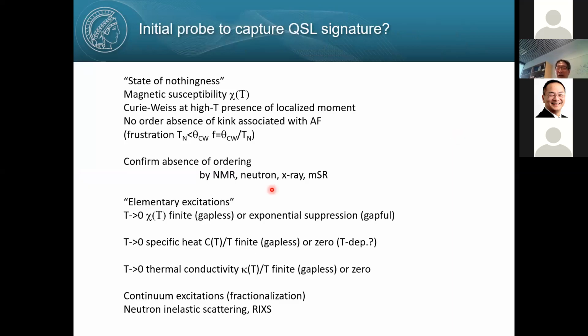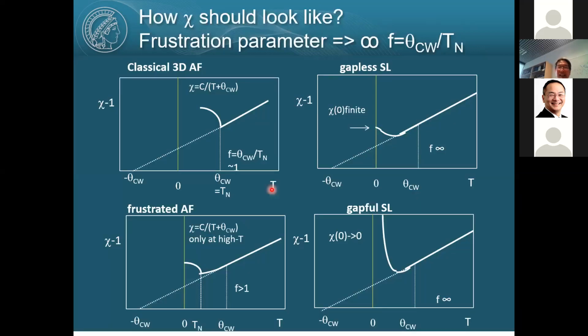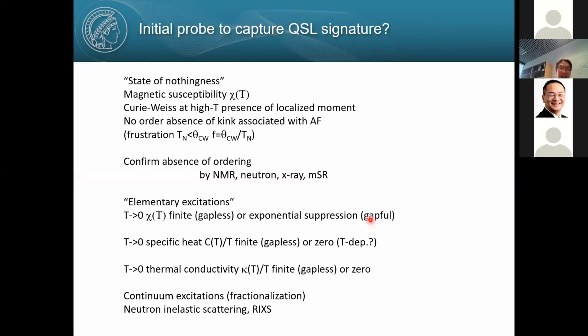Of course, magnetic susceptibility is not a very sensitive probe of magnetic ordering, and you should confirm the absence of ordering by NMR, neutron, X-ray, muon spin rotation, or specific heat. Once you find the absence of ordering, you want to identify the elementary excitation. The easiest is to look at magnetic susceptibility. If you have a gapless spin liquid, you have something like Pauli susceptibility, so finite susceptibility in the T equals 0 limit. But if you have a spin liquid with a gap, susceptibility goes to 0 exponentially. That's how you can identify a gap. And of course, if you have a spinon Fermi surface, it is gapless, so you have finite susceptibility.